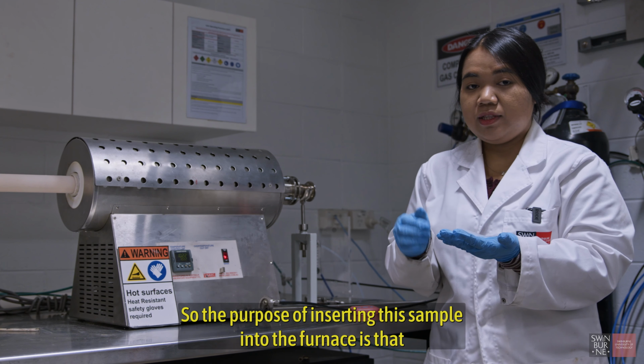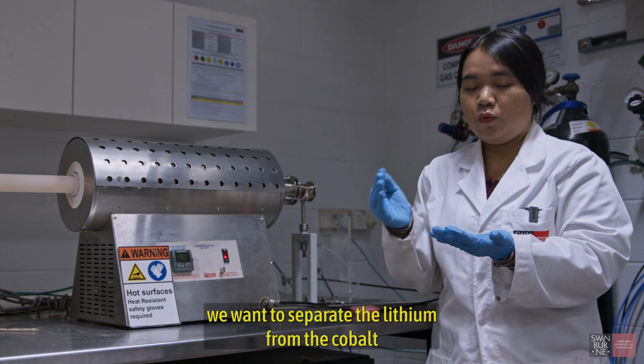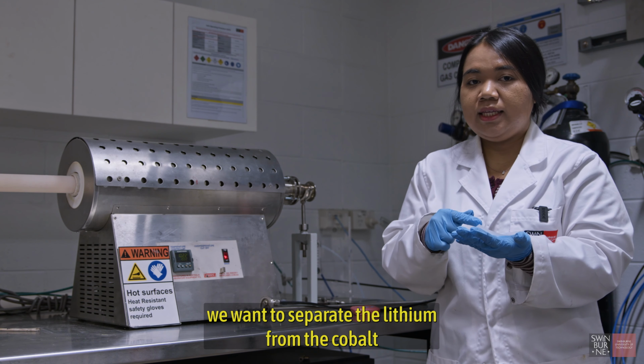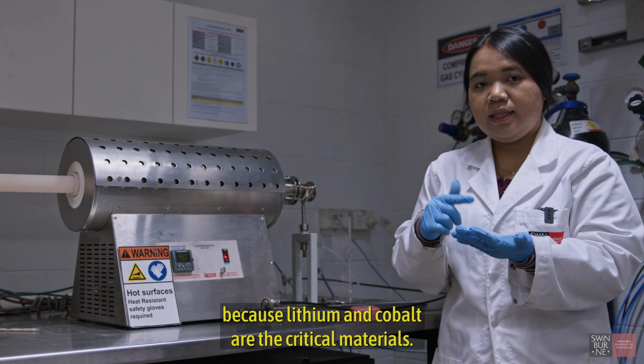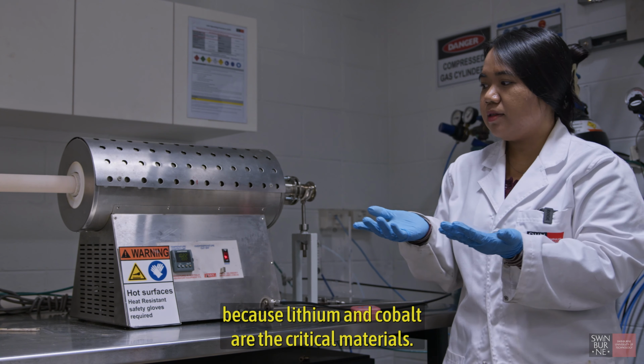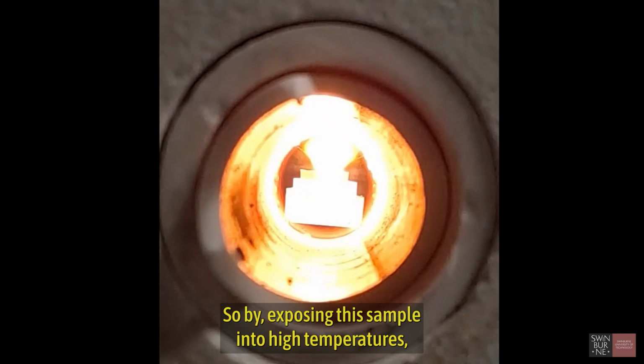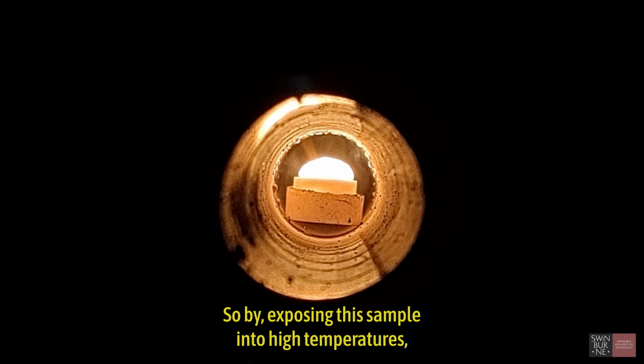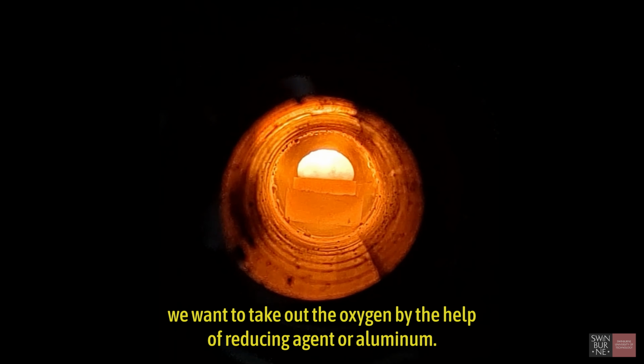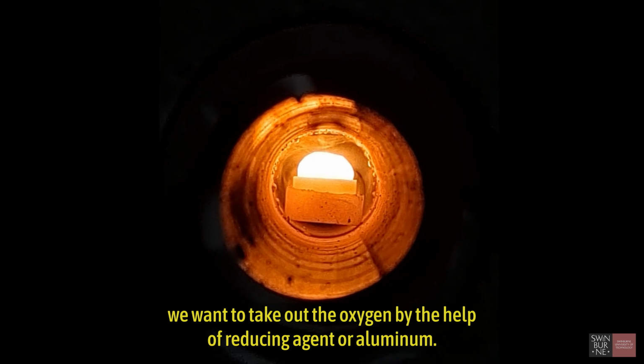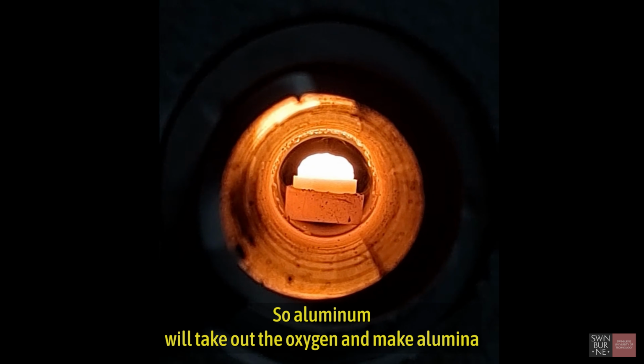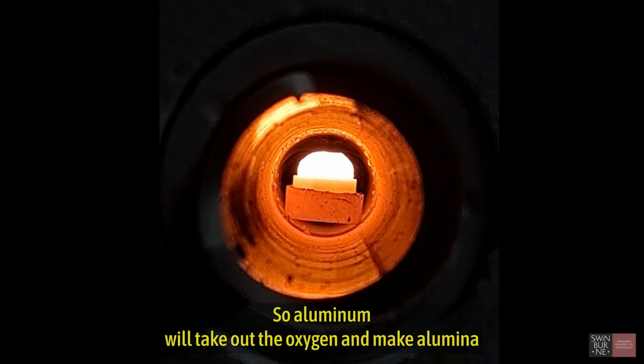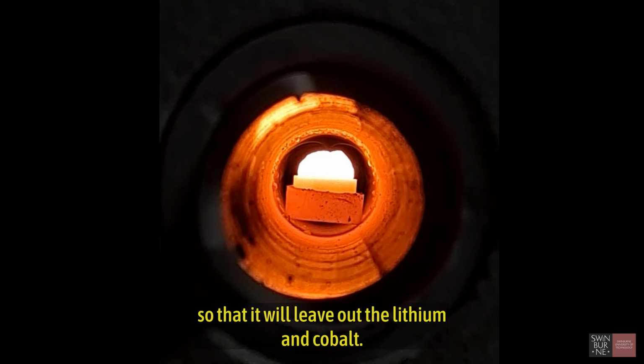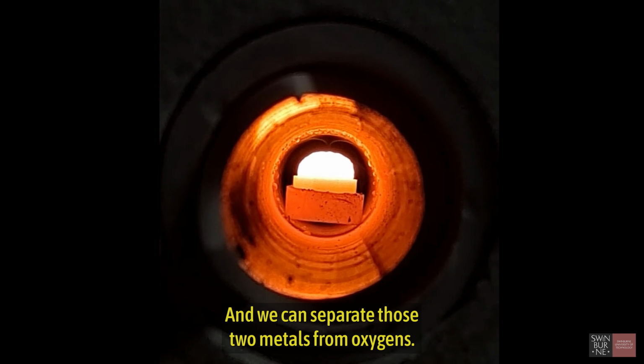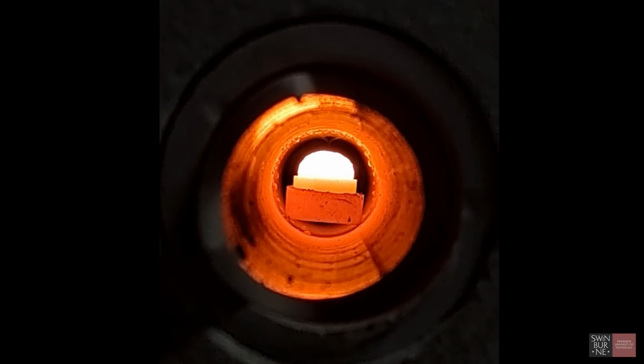The purpose of inserting this sample into the furnace is that we want to separate the lithium from the cobalt, because lithium and cobalt are critical materials. By exposing this sample to high temperatures, we want to take out the oxygen with the help of a reducing agent, aluminum. Aluminum will take out the oxygen and make alumina, so that it will leave the lithium and cobalt, and we can separate those two metals from oxygen.